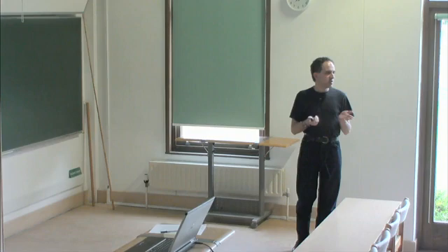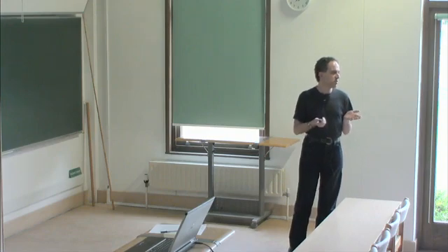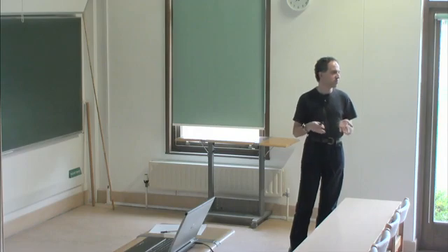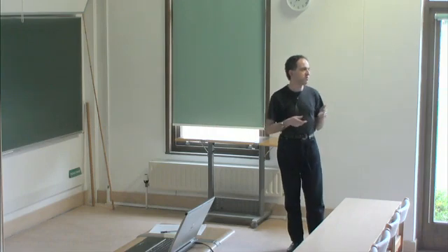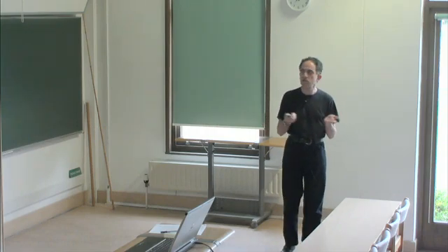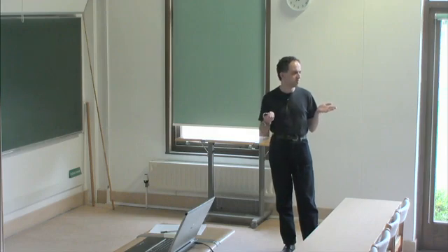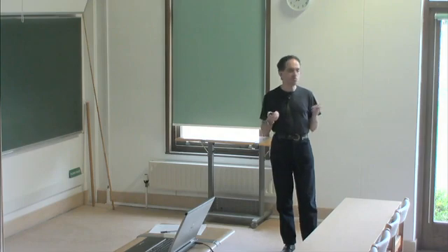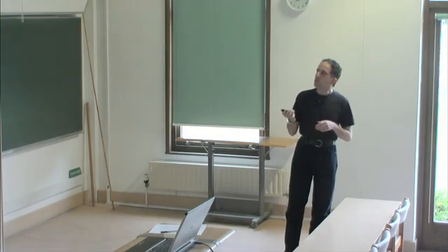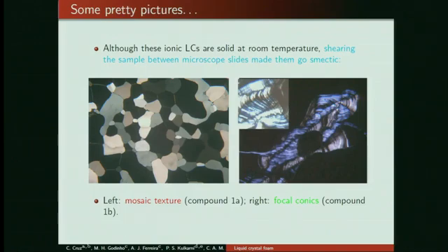Well, it so happens that these are fairly weak solids made up of stackings of long chains. So maybe just shearing them is enough to, quote unquote, melt them into the smectic phase. But it turns out that they can survive in that state for at least 1 day or maybe longer. So we believe this is a non-equilibrium state, but a rather long-lived one. Well, this is not all, because it gets even more interesting.